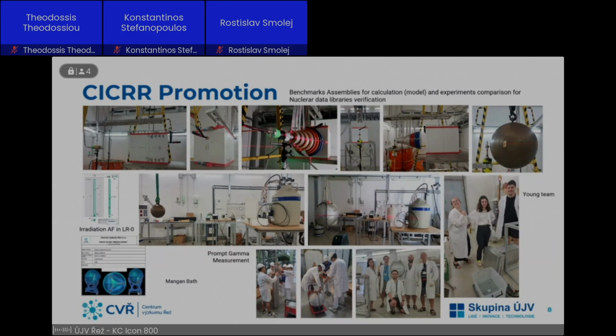This is the case with this high purity germanium detector. This was again in the frame of the open access, which was applied for by the Technical University in Ostrava. They were interested in the prompt gamma measurement from the leakage from the iron, polyethylene, heavy water, and other materials. So we prepared the laboratory equipment for them, and they just brought the high purity germanium detector. We filled it with liquid nitrogen, and they performed the measurement. To show that we are not only alone and older people here, we have a young and nice employee or collaborator here. And this is staff from Ostrava.